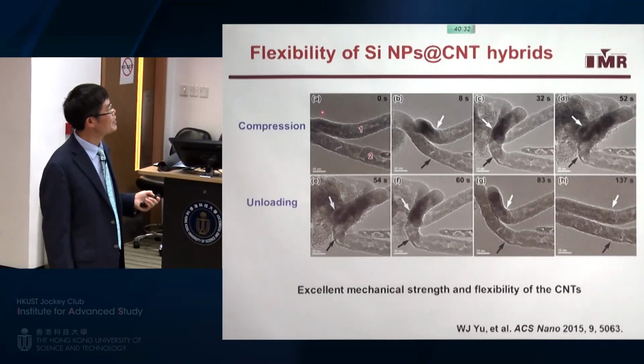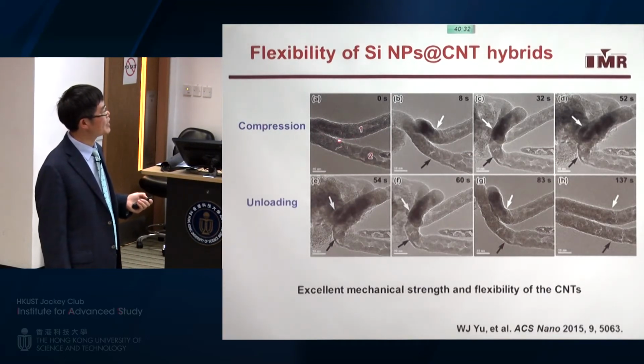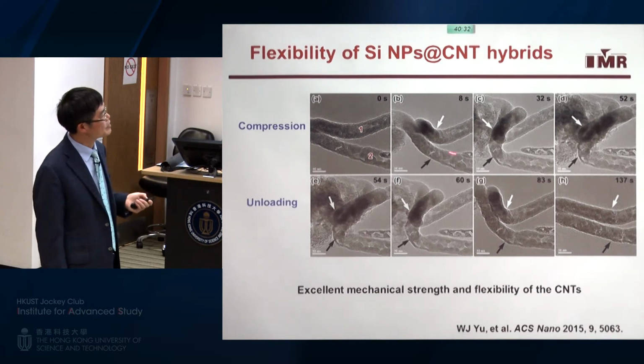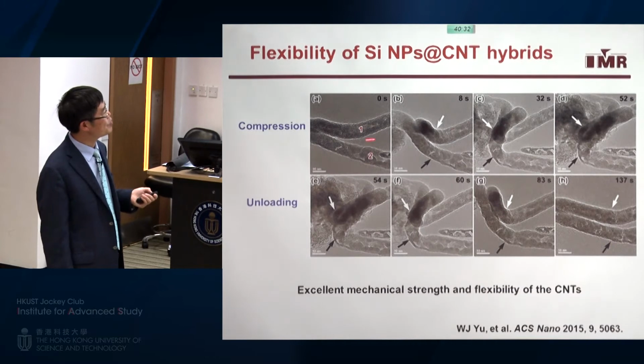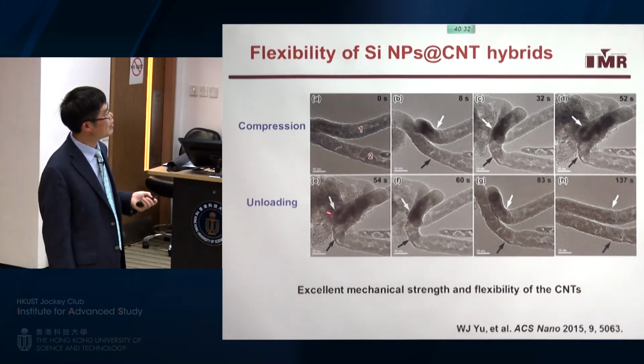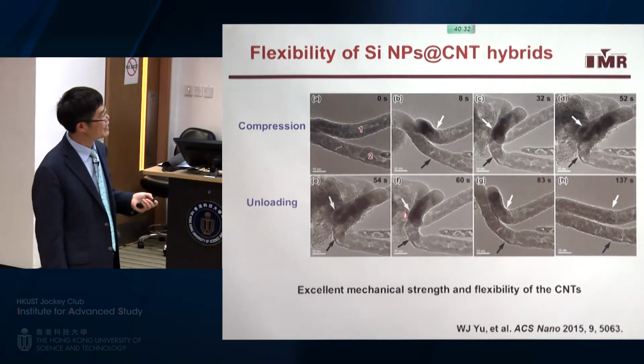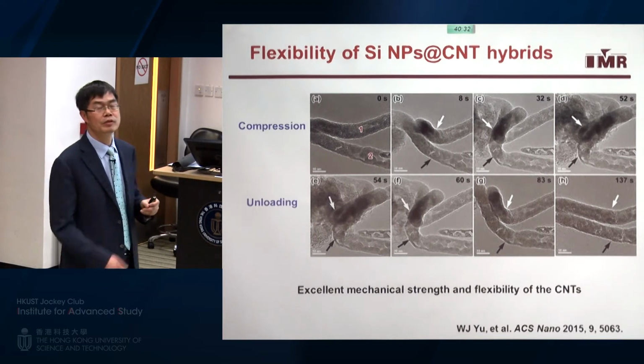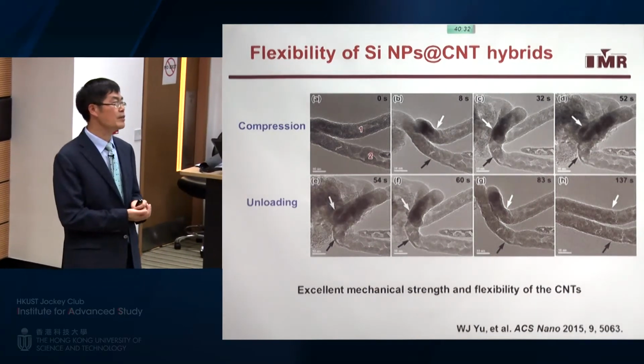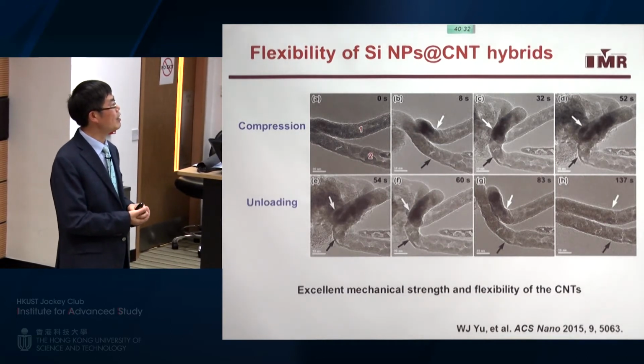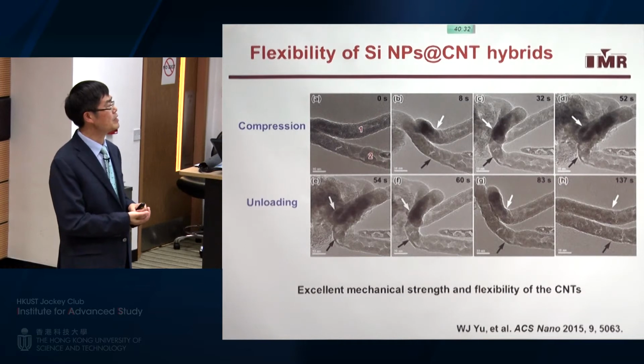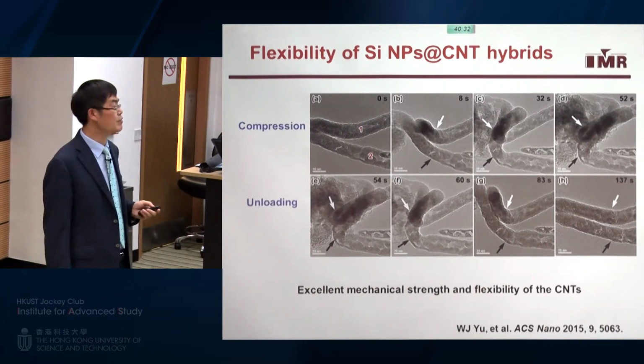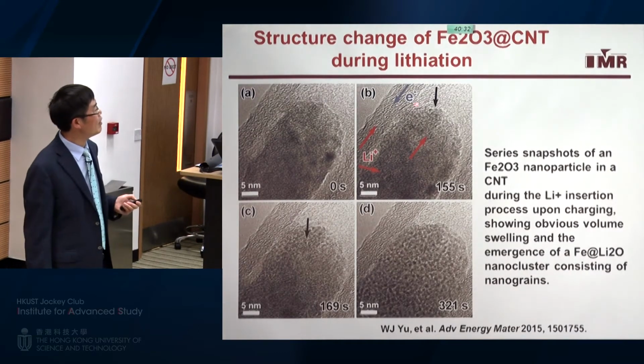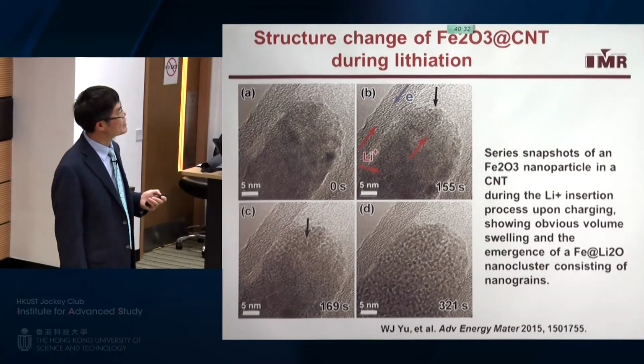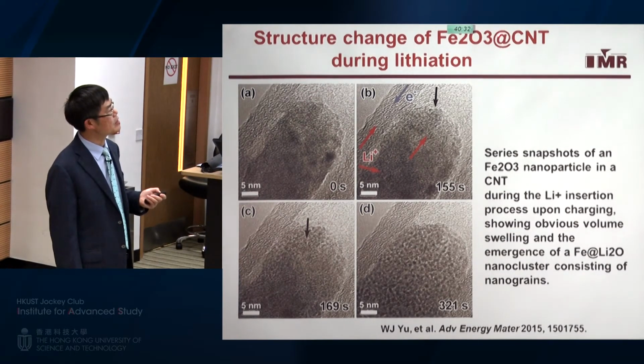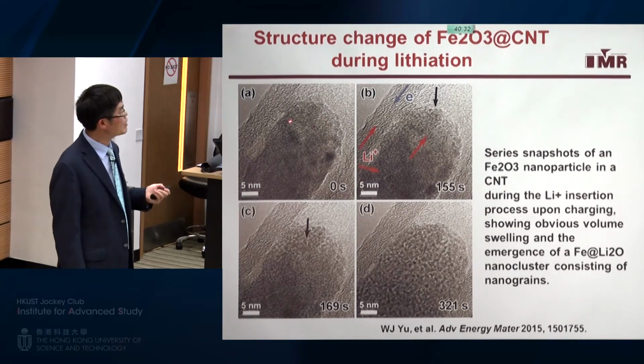And we have also tried to investigate the flexibility of this material. We can push it, and then after unloading, the carbon nanotube can return to its original morphology. That means this material has some flexibility, which may be useful for making flexible batteries. And this is another example. We have iron oxide particles, which also have quite a high capacity, confined in the carbon nanotubes.